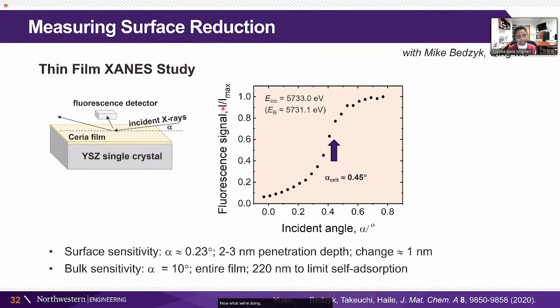Now, what we're doing with the XANES study is grow a thin film of ceria and change the incident X-ray angle that we're delivering the X-rays at, because if we're at a very shallow angle, then we are below the total internal reflection, and we get a very small, weak signal, but that signal is entirely from the surface. When we're at a large angle, and we typically do it around 8 to 10 degrees, then we are probing the entire bulk. So we're going to be either skimming the surface at this very shallow angle of around 0.2 degrees, or we're going to be at a large angle where we can detect the entire film, and the film is around 220 nanometers in thickness.